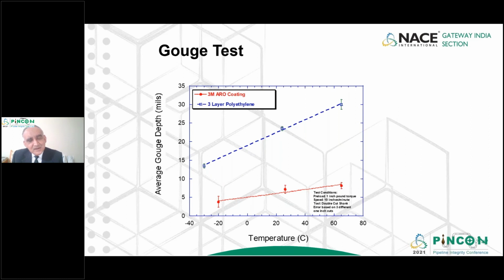Now, why we did this comparison is because in our country, especially in India, when a pipeline is being constructed, typically the outdoor temperature is about 30 to 40 degrees Celsius. So if we do the gouge test, which is a simulation of backfill, like earth material which is taken out from the trenches or put back after the pipeline is put into the trench, these have got a lot of rocks and hardened pieces of earth, which go and impact the pipeline. That's something like gouging the coating.